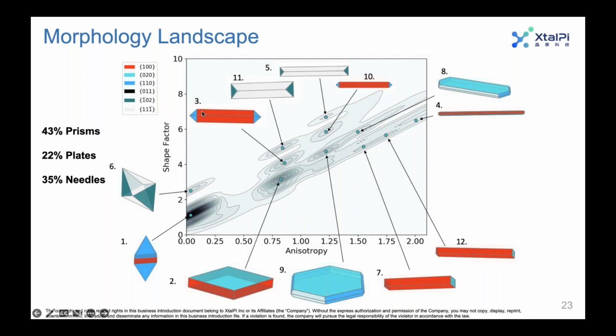And then we took similar morphologies and we grouped them together to give you an idea of the distribution. Based on the morphology landscape, 43% of the predicted morphologies are prisms, 22% are plates, and 35% are needles. So there is a high chance of obtaining prisms for metformin HCl, but there's also a significant risk posed by needle morphologies.